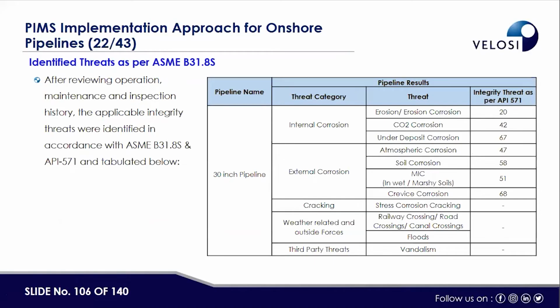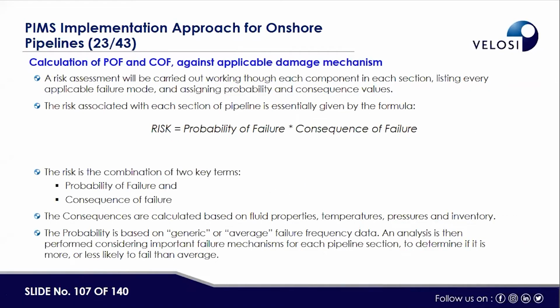Like these were the threats which were applicable in this particular case: internal 20, which is erosion corrosion as per the API 571 tag number, then CO2 42, then under deposit 67. External 47, 58, 51, 68. Then from a cracking point of view, these were considered with no API 571 reference, but we have assessed all this. Then for calculation of PoF and CoF, this approach was used.